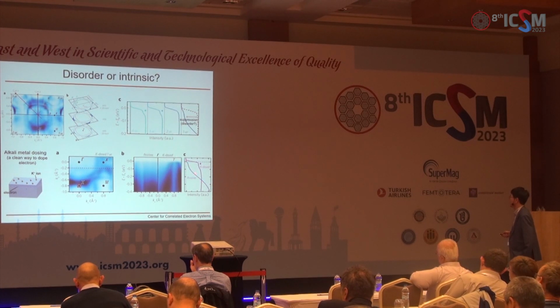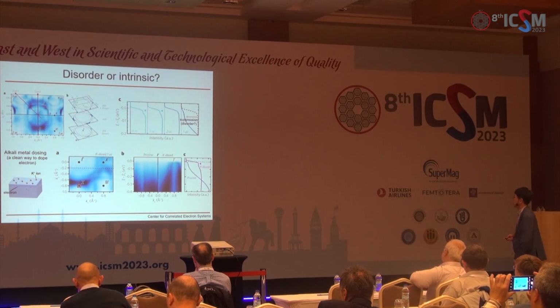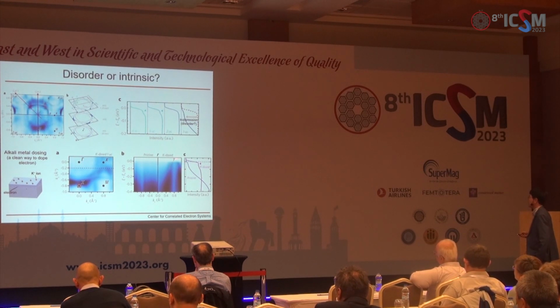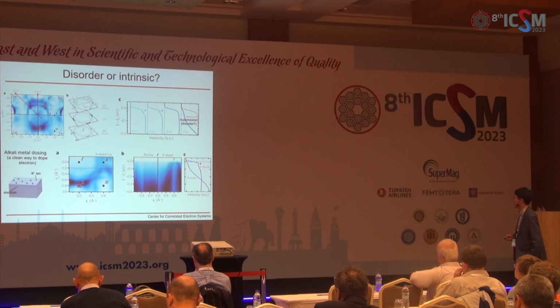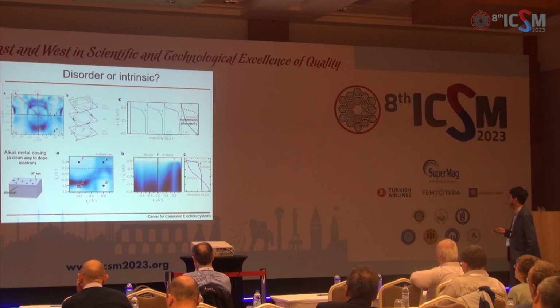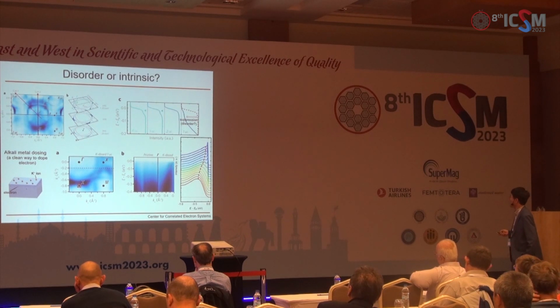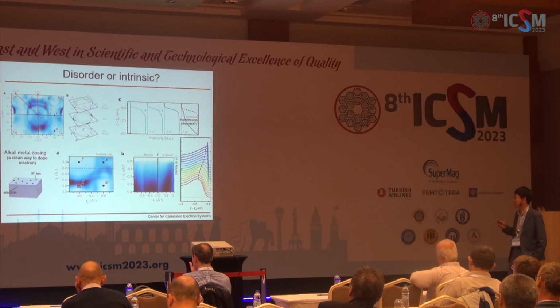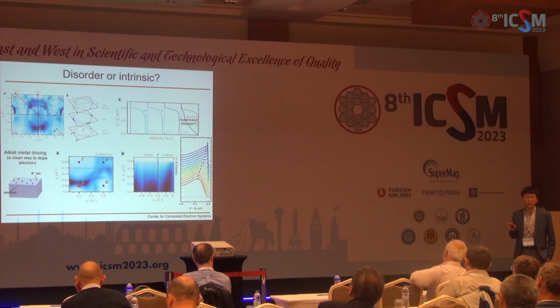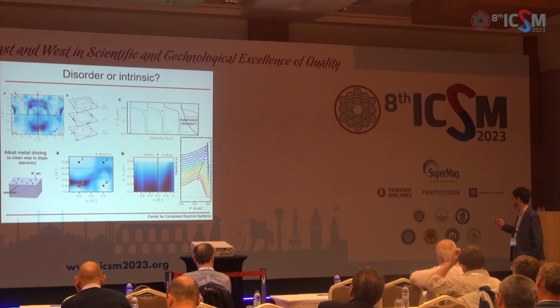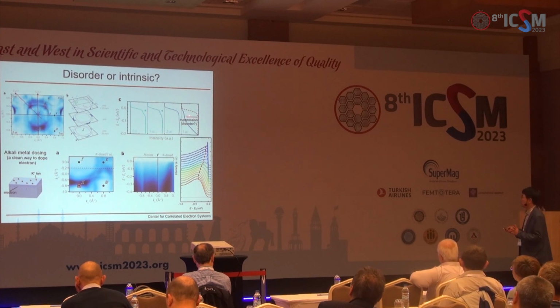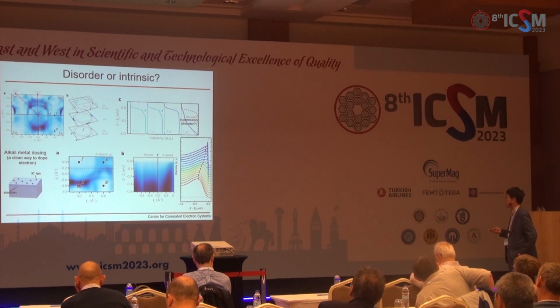So here's a pristine film without potassium. Here's a potassium doped film. The spectral weight grew as well as this quasi particle. The quasi particle grows. Now it's very clear. It's fairly weak here. And if we put down more electrons, this quasi-particle grows, and this quasi-particle is extremely sharp. That means this disorder effect does not play a role here. So whatever this suppression is, that's not due to disorder effect.